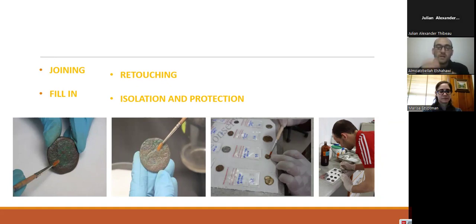At some point we can do a retouch with a different color, but we have to write this in the whole treatment report. And as I said, at the end we can make isolation and protection using a coating, using Paraloid like 10% in acetone, or you can use corrosion inhibitors, as scientific research is going toward using natural extracts from plants. At the end, also, if you have a very good surface, very flat, very smooth, you can use microcrystalline wax. It is good as a protection layer for ancient coins.